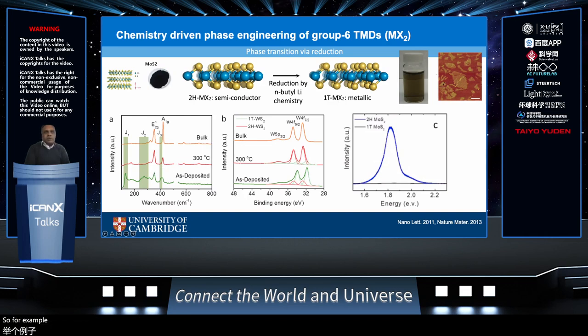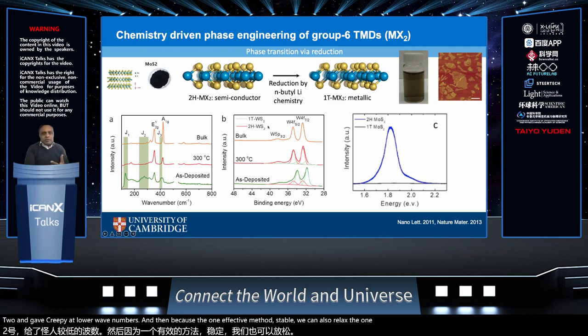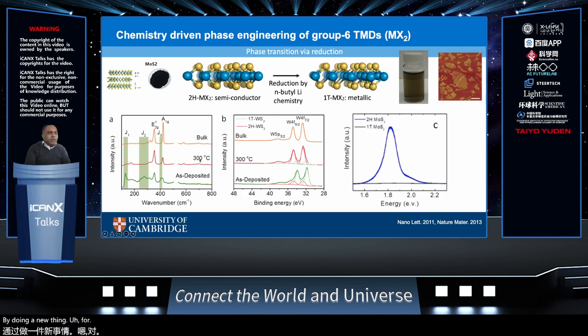So for example, if you were to measure Raman after exfoliation, you would see these characteristic J1, J2 and J3 peaks at low wave numbers. And then because the 1T phase is metastable, we can also relax the 1T phase back to the 2H phase by annealing for a couple of hours in an inert environment. By annealing at 300 degrees C, we see that the J1, J2 peaks disappear, and we have the emergence of the usual E1 and A1G peaks that you get in a typical MoS2 crystal.